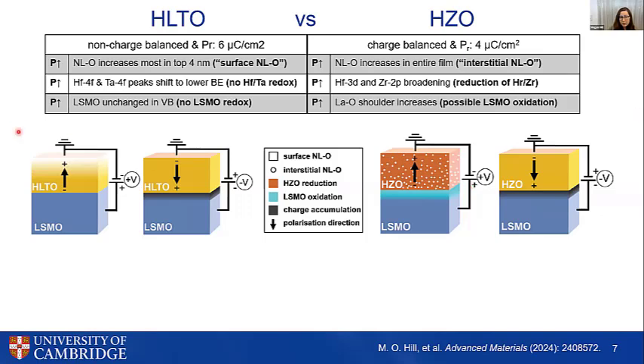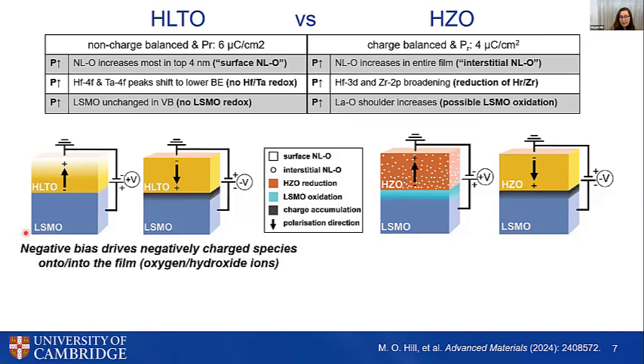I didn't show this data, but we do have some evidence that we have some LSMO oxidation when we have HZO reduction, but then no such effect in the HLTO. So what we think might be going on here is that when you apply a negative bias to switch your sample into the P-up condition, we can get negatively charged species that are being driven into the film and onto the film surface. But in the HZO, we actually are getting a local reorganization of oxygen with reduction of HZO and potential oxidation of LSMO. This isn't a mass migration, but just a really local reorganization that we seem to be observing.